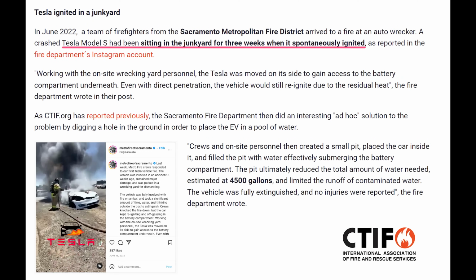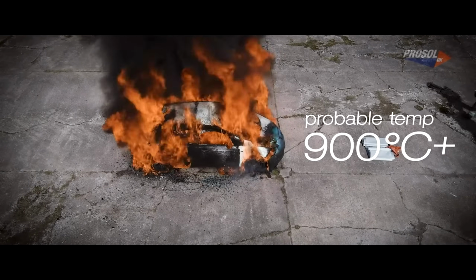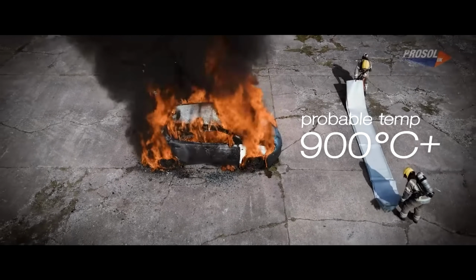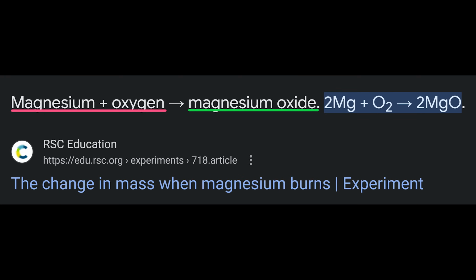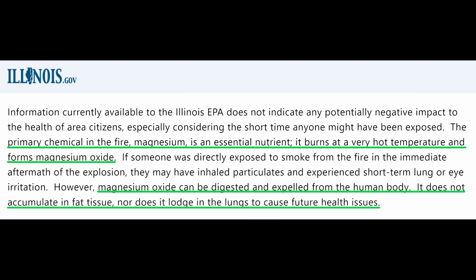That's as opposed to battery fires, which arguably pose a greater challenge for firefighters. Why? First, because battery fires are self-sustaining electrochemical fires that can reignite weeks after the fire is presumed to be out. Second, because there's usually about 1/4 ton of battery cells in an EV that are encased in a metallic enclosure deep in the core of the vehicle, which means they can be difficult to access and extinguish and can take days to cool off. Third, because they generate toxic fumes such as hydrogen fluoride. That's as opposed to magnesium, which reacts with oxygen to form magnesium oxide, which the body can process.